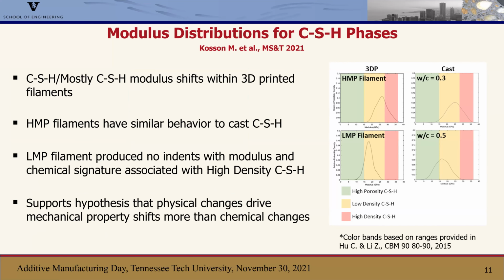When we separate indents using EDS by their chemistry and then only look at certain hydration products, we're looking here at calcium silicate hydrate gel, which is one of the most important hydration products for a cement material. What we see is that even when you sort for the chemistry, you're still seeing those big changes in the mechanical properties between the low mechanical property filaments and the high mechanical property filaments. And that's still mirroring what we're seeing in the samples cast with different water to cement ratios. So that further supports our hypothesis that it's being driven by water availability, but also that these changes are being driven more by changes to the mechanical structure rather than the chemistry of the hydrated products.